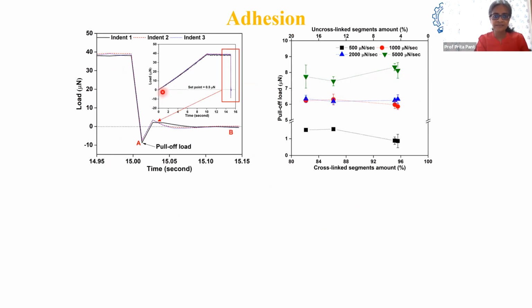So this is the load versus time. This is the load function that we gave. We load up the sample, we hold it for a longish time, and then we very quickly unload, just yank it out as fast as we can. And we turn off the feedback, because otherwise it's going to try to bring the load back to 0 and stop there. So when we turn off feedback, then it goes down to this point, to a negative load, which basically means the tip is kind of being sucked by the surface, and we have to pull against that.